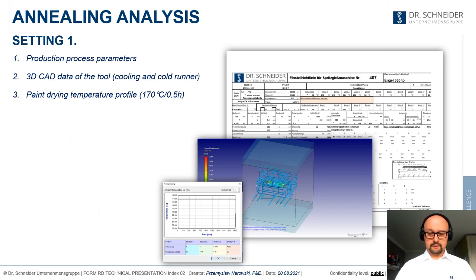And that's how we did the annealing simulation. So we use the real process parameters from the injection molding machine, not the default ones or some kind of computed values. We use the 3D data of our mold to have the cooling circuits and the cold runner geometry. And of course, we introduce the temperature profile from our painting and drying process, which in this case is quite simple. It's just 170 degrees. We are just keeping the part at 170 degrees for half an hour.